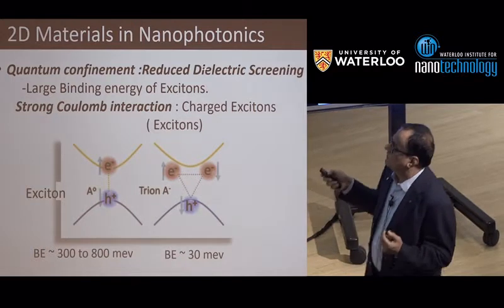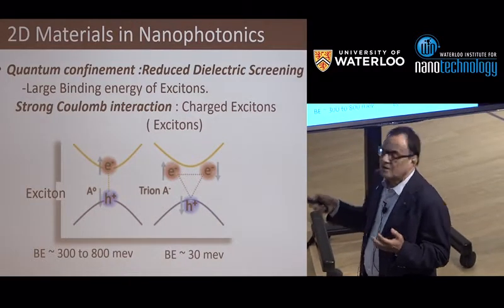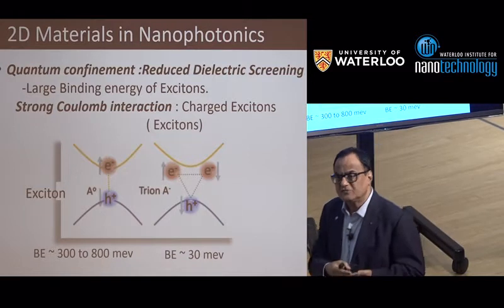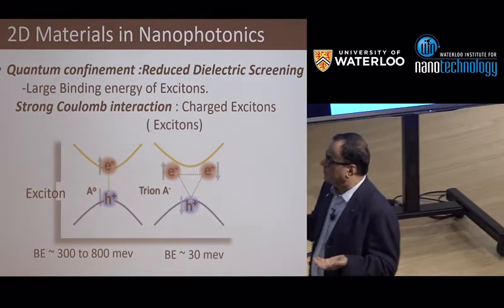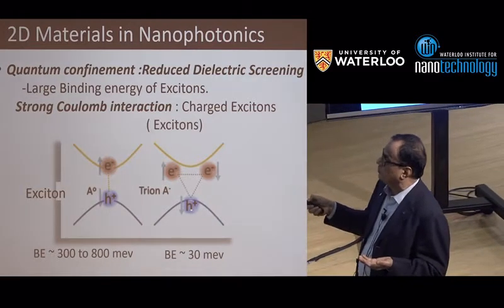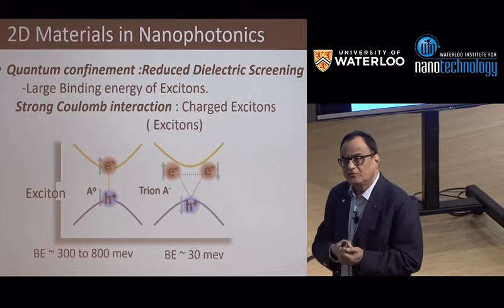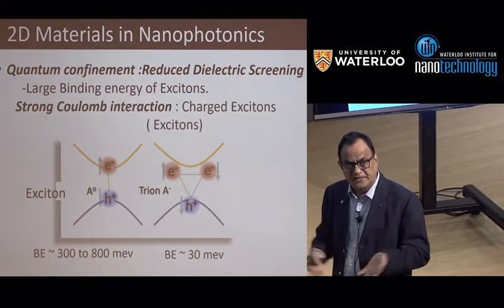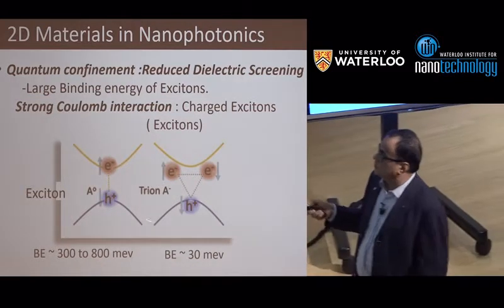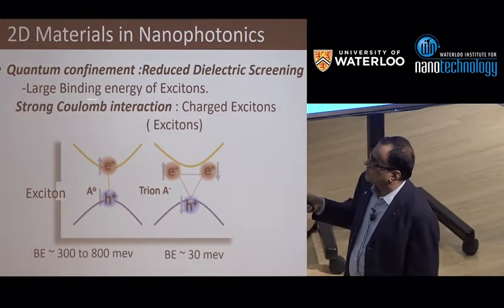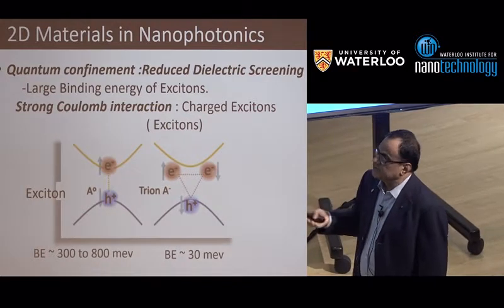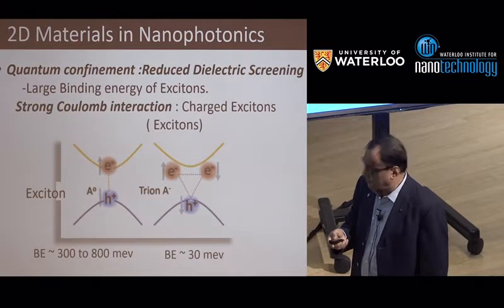So you have reduced dielectric screening, so you have large binding energy of excitons, and of course trions also, where you can get 2 electrons and a hole bound. All that is beautifully seen even at room temperature in MoS2 and a few other 2D materials. So you have strong Coulomb interaction, which is the key point of these 2D materials.